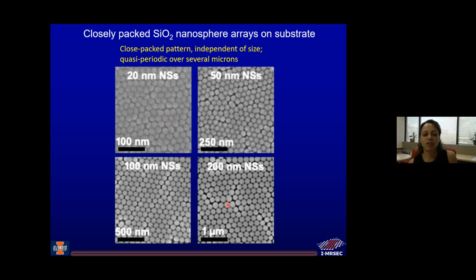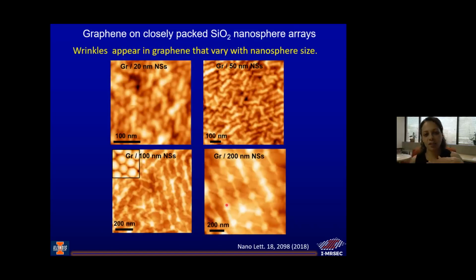Okay, so now what happens when we put graphene on these? So this is the same sort of nanospheres, but now with graphene on top of them, and these are AFM images now. Okay, so now what do we see? So here's graphene on 20 nanometer nanospheres. And what you see is basically something that's kind of uniform. It means that the graphene is basically uniformly conforming to the top of these nanospheres. Okay. Now we see graphene on top of 50 nanometer nanospheres, and suddenly these bone-like structures and zigzag structures appear. And I found this really cool because you know that there's graphene on there. So what is this? It turns out that all of these features are wrinkles. Okay, so on the left, on the 20 nanometer graphene, it's just conforming.